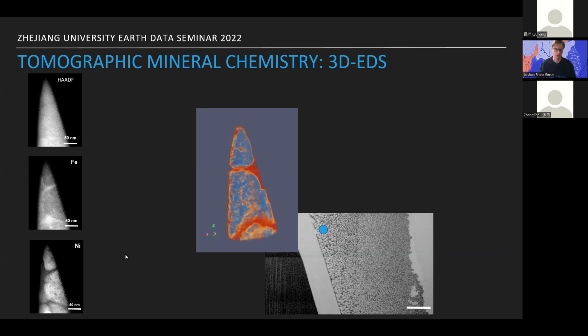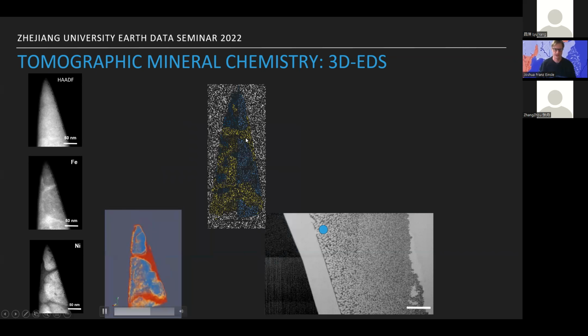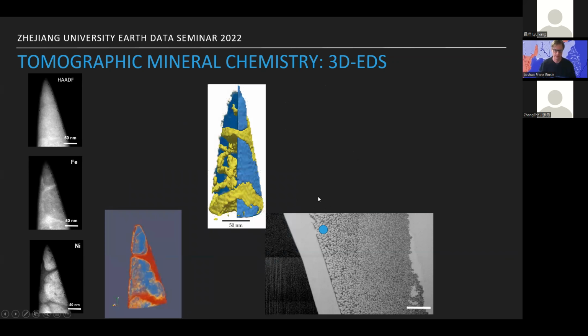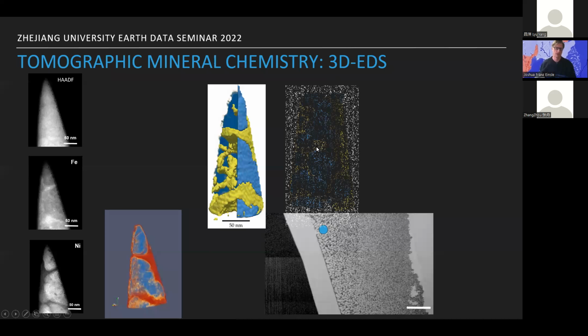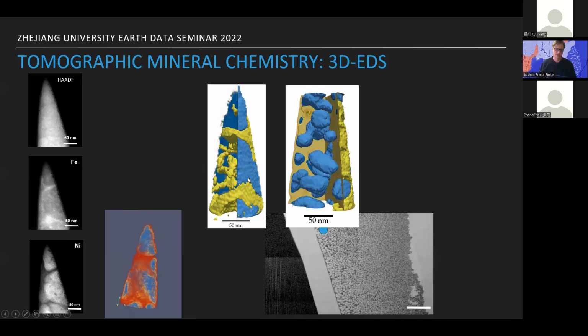And so we have a coarse cloudy zone here, and we have a fine or a medium one. In the coarse zone, the big blue tetrataenite islands are on the order of 200 to 250 nanometers, whereas in the medium zone we're talking more about 100 to 50 nanometers in size. But regardless, what we first saw is that in the coarse cloudy zone, the large tetrataenite particles are actually interlaced with remnant and relic bits of matrix material.